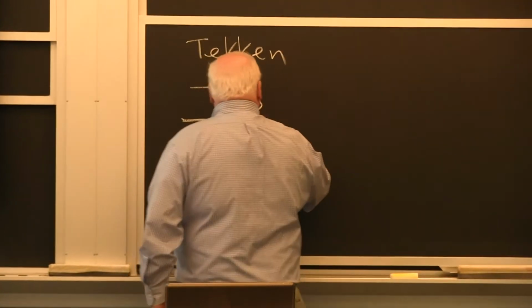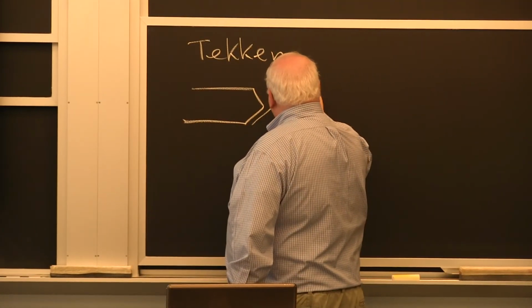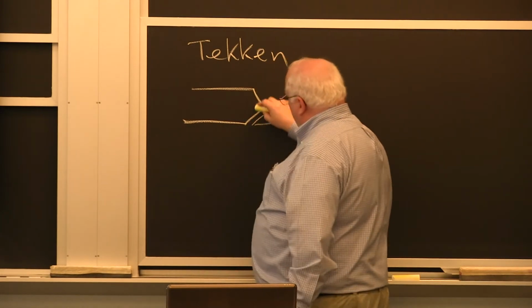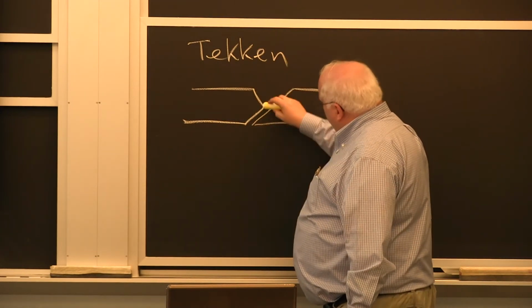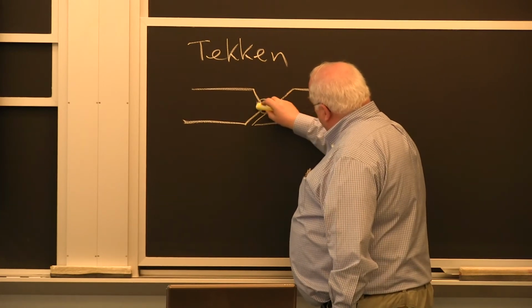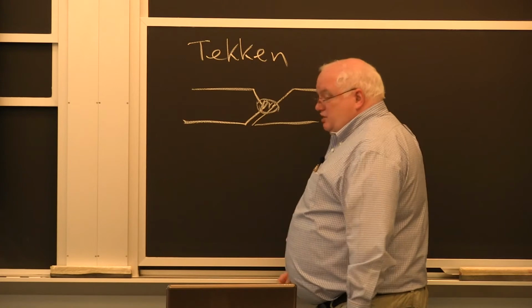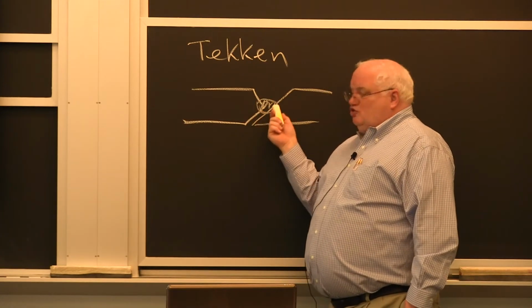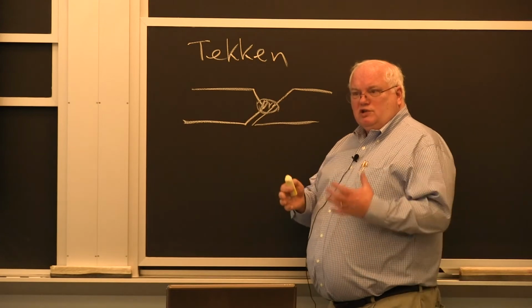Now, when I was a welding engineer at Bethlehem Steel in the mid-70s, the Japanese liked to use the Tekken test. The Tekken test was nothing more than, you take like a 1-inch plate or a half-inch plate, and you cut one of them in cross-section like that, the other one you bevel straight across, so you do a double bevel on one and a single bevel on the other, and you put a little weld right in here. And you see if it cracks. Because in the Tekken test, there's tremendous residual stress here, even though you're only using small plates.